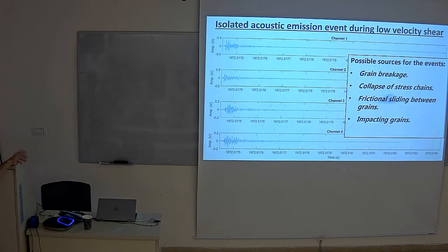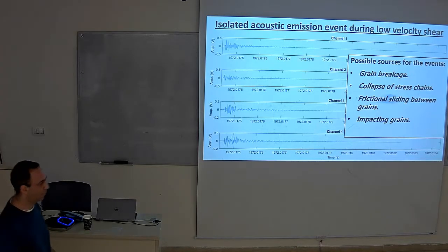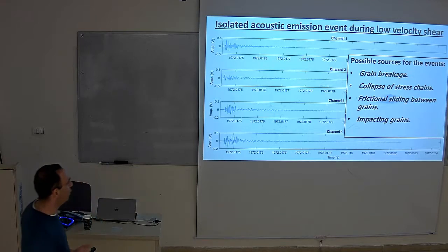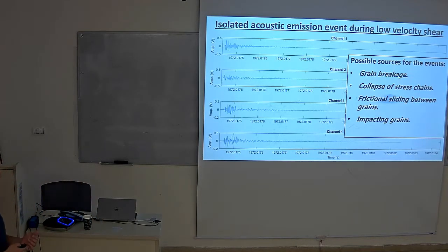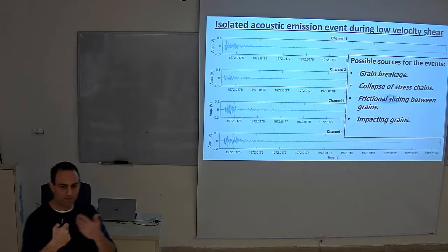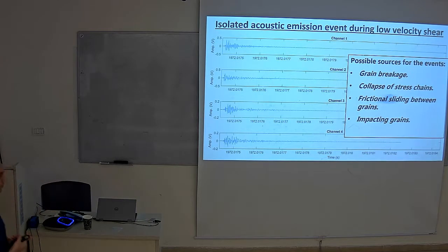This is during a low velocity experiment, when we can see isolated events separated, and we can have different sources for events. We can get grain breakage, collapse of stress chains, frictional sliding between the grains, like stick-slip between two grains, or impacting between the grains, as we should observe in the grain inertial regime. So the first three are supposed to appear because of things connected to the physics of low velocity, the quasi-static regime, while impacting grains is supposed to be connected to high inertial numbers and high velocities.